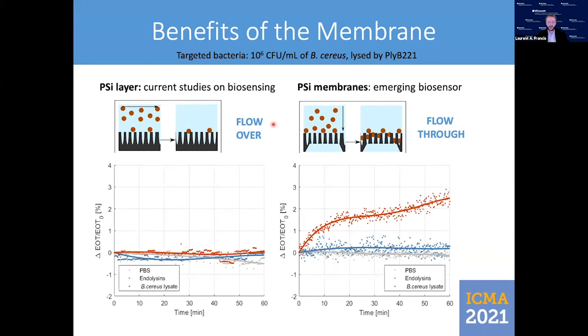For our device, we use the flow-through approach with our porous silicon membranes. This enables the capture of a lot more of analytes. And for an initial concentration of 10 to the power 6 CFU per mL of our bacteria, an increase of more than 2% in the relative effective optical thickness was measured after 1 hour.